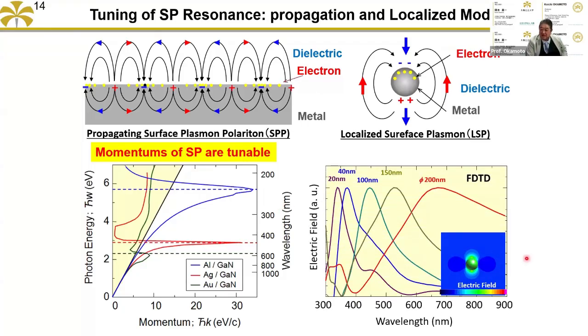On the other hand, in the metal nanoparticle case, by changing the size and shape of the metal nanoparticle, you can control the resonance peak. But there is no momentum, so you cannot control the matching condition. Easily you can control the wavelengths, but it always involves some energy loss, and 100% coupling is difficult. So there are some advantages and disadvantages of these two modes.